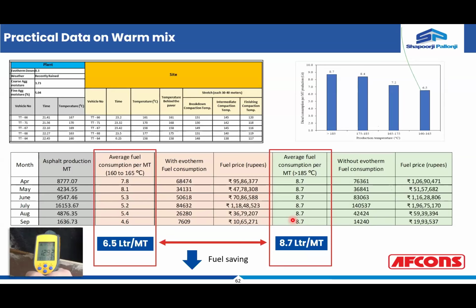That gives you an indication that there is a reduction of more than 2 liters per metric ton of production of asphalt. And if you remember, currently the fuel cost is close to 100 rupees. If you are able to save 2 liters per metric ton of asphalt produced, you are saving 200 rupees per metric ton of asphalt in the process.